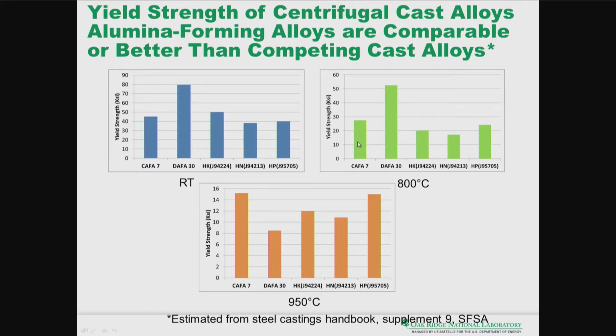As you bump up in temperature, of course, all the strength levels drop. The highest here is 60 KSI, for example. And you can still see that the CAFA 7 is starting to assert itself again, and the DAFA 30 definitely has much better strength properties at 800 C. And going up to 950 C, the CAFA 7 really starts to hold its own, and as you can see, the DAFA 30 has now significantly dropped in strength. This is directly related to the fact that the strengthening precipitate is disappearing at these higher temperatures. So in terms of strength, in the DAFA 30, we are limited to temperatures of about 900 or so, which is also consistent with its oxidation performance.